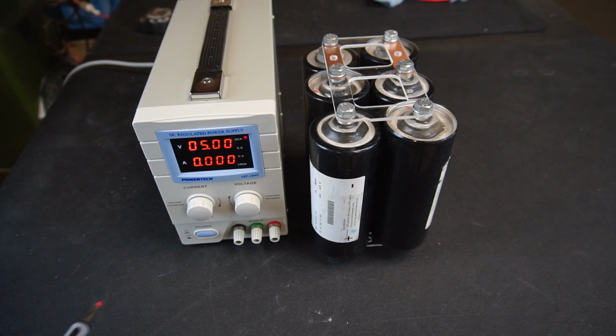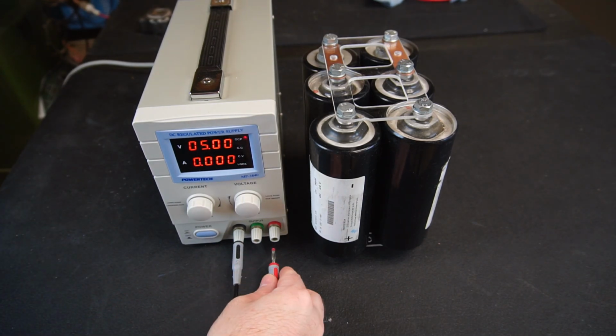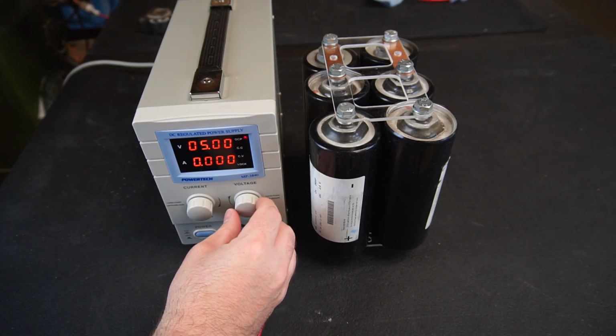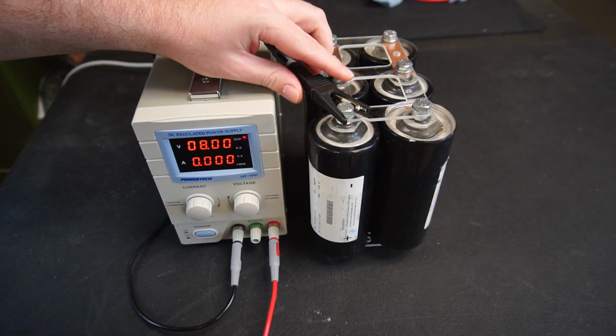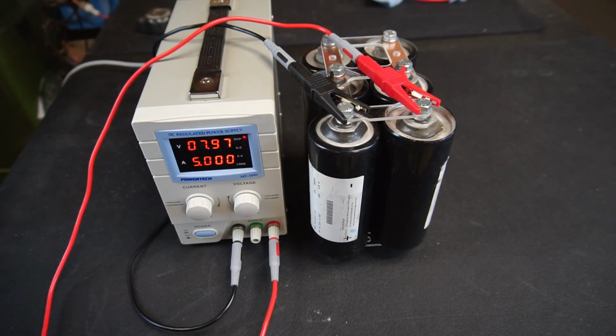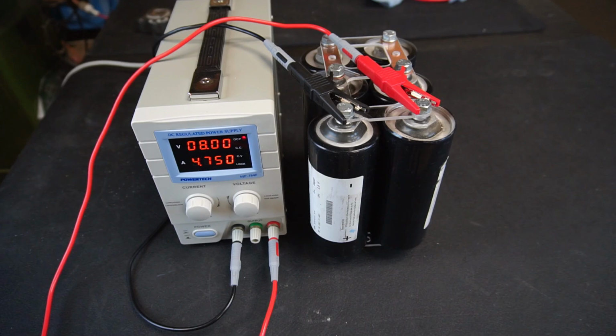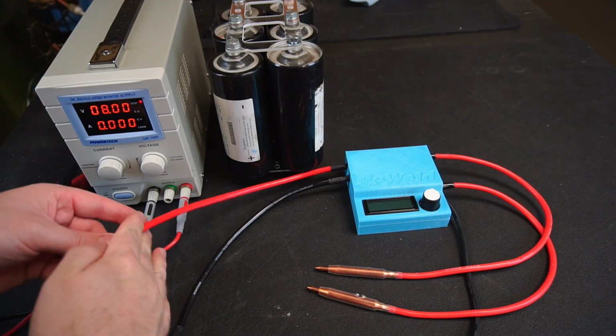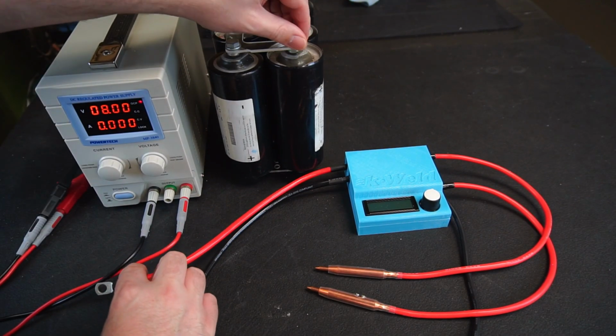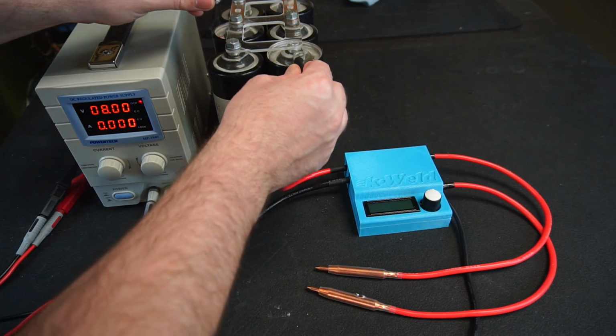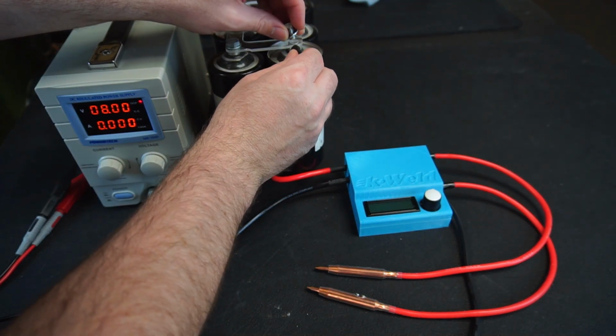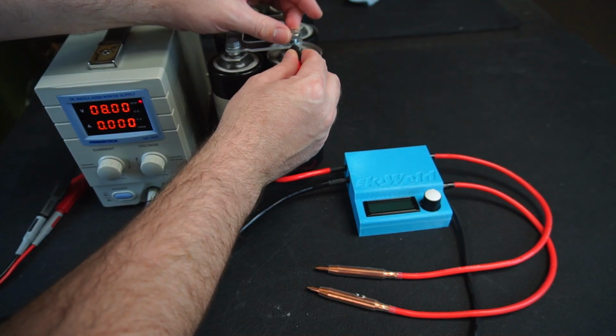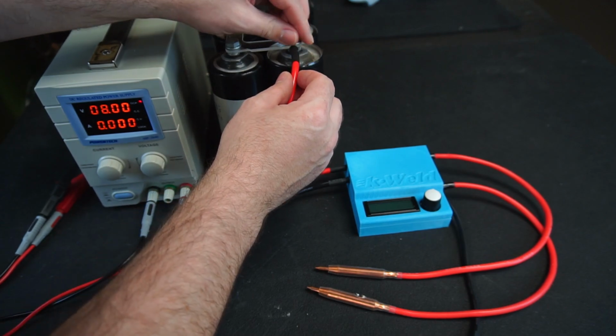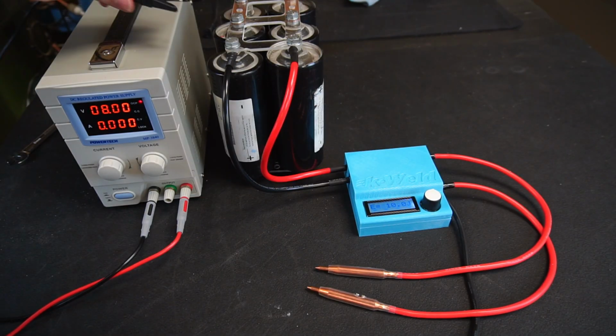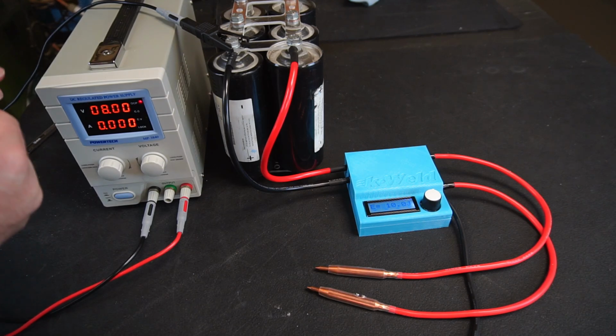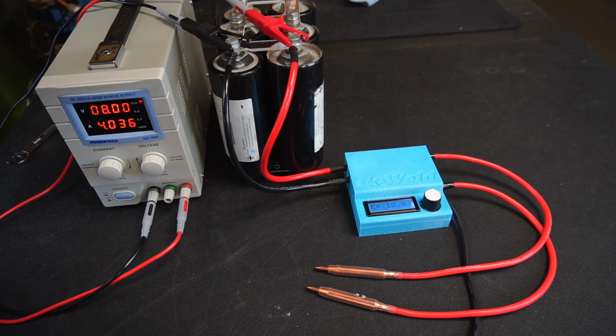The only way to limit current is through voltage control, so I set my power supply to 8 volts and charged up the caps. Later I can increase the voltage until I hit the 1500 amp sweet spot if needed. The cables are directly bolted to the super caps, which kinda scares me because if I do something wrong and need to switch off the power quickly, well it just isn't gonna happen. However, throwing caution to the wind and having my mother on speed dial, I proceeded anyway by connecting my power supply to the caps to continually top up the caps as I weld.